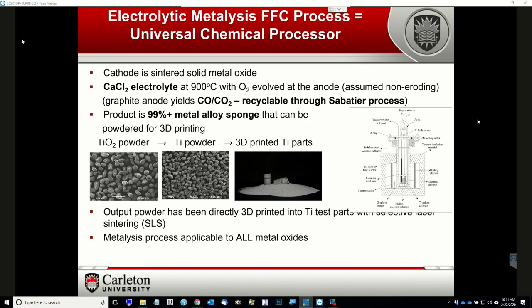Now this sponge can also be powdered for 3D printing, and this has in fact been demonstrated. The solid state cathode on the left, the picture on the left of powdered rutile, is then reduced into titanium powder, and this has been subsequently immediately injected into a selective laser sintering system to create some various test parts. Now the Metalysis process is applicable to all metal oxides, so it can also be used to reduce iron oxides, aluminium oxides, and various other types of oxides. It yields a very, very high purity metallurgical material.